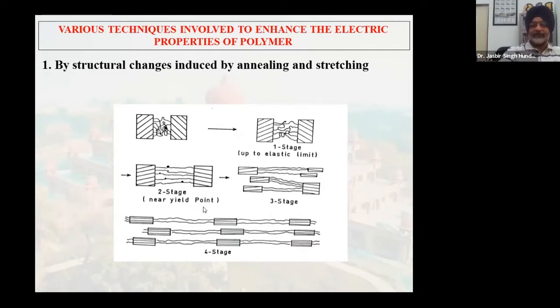That is one thing, crystallinity increases. Second, the spacing between the chains gets reduced, and hindrance to the movement of dipoles gets reduced. But if we stress too much, then the chains may simply fall apart like this. So the electric breakdown of the material will happen sooner if you reach stage 3 and 4. So stage 2 is the one that we find is the best to use here.